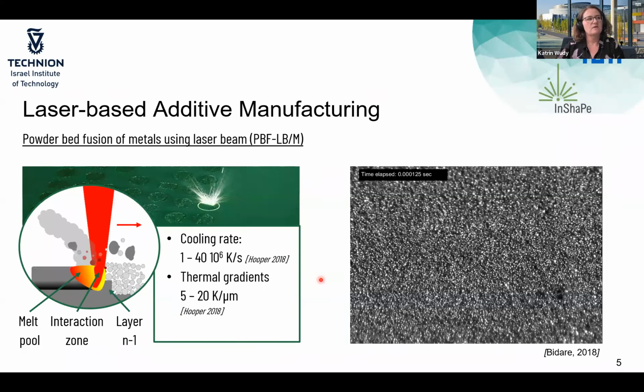And if we have a look at a typical process window with a Gaussian beam profile, and as material we used a standard material for powder bed fusion, which is stainless steel. And what you can see there, you conduct all of these experiments and analyze later on the welding line. So you analyze on one substrate plate, for example, the welding line and the energy input. And what you can see if you are in a range of stable processing is that the welding depth is quite similar to the welding width.